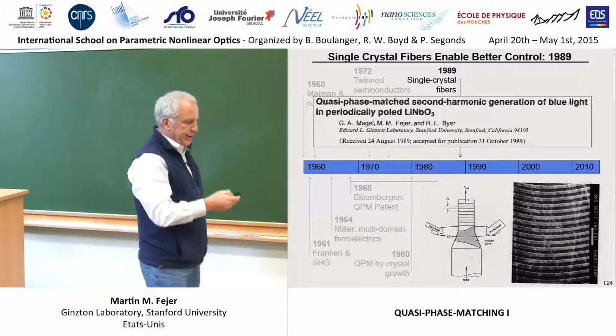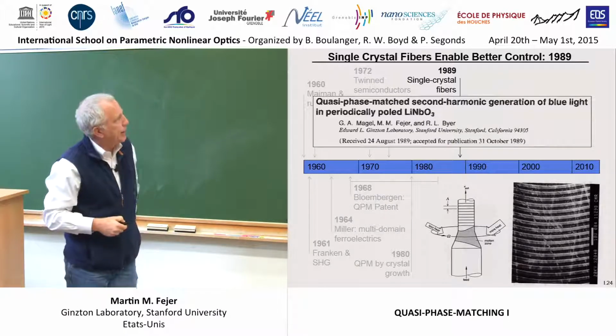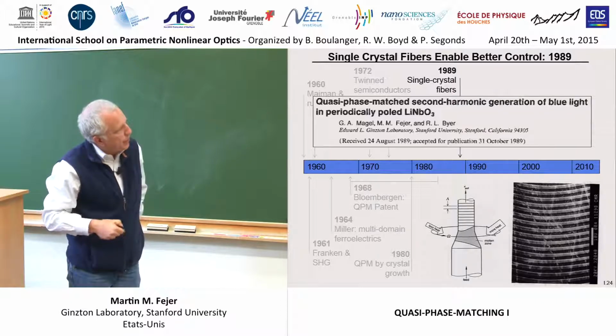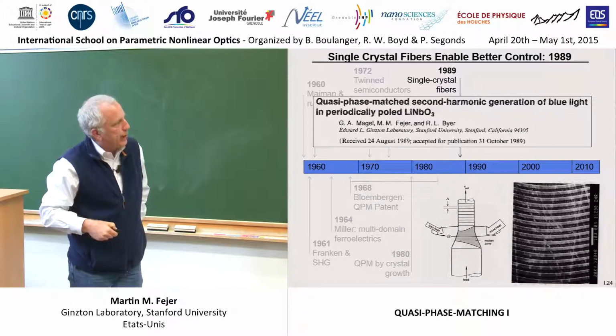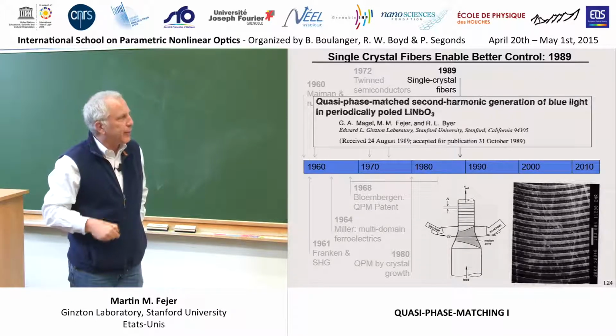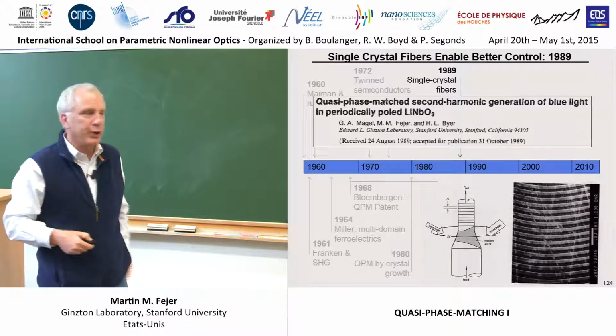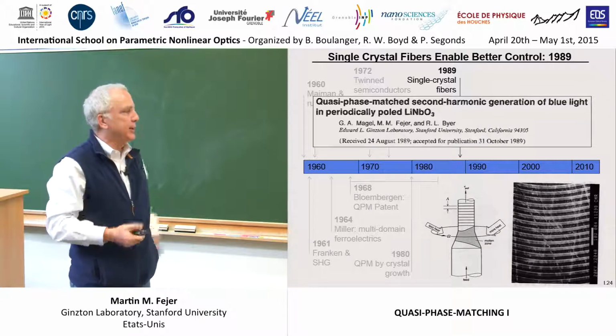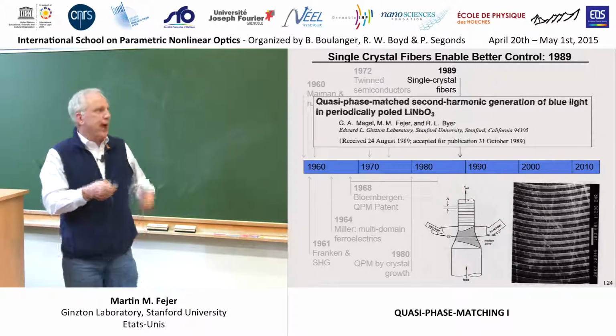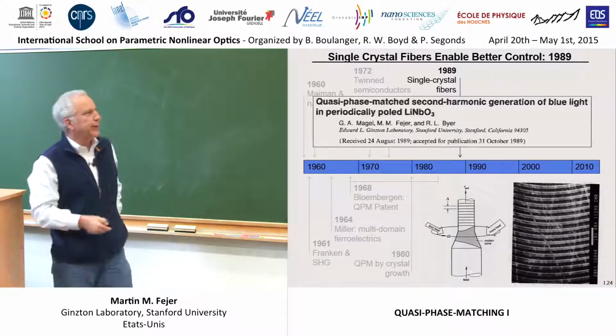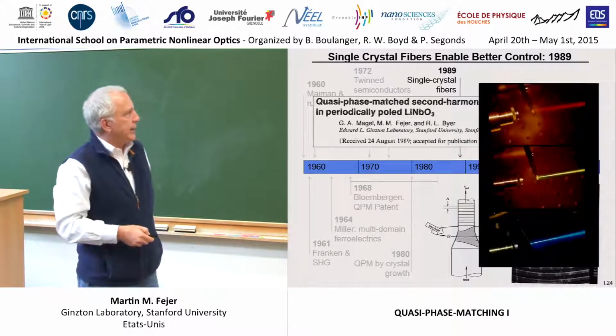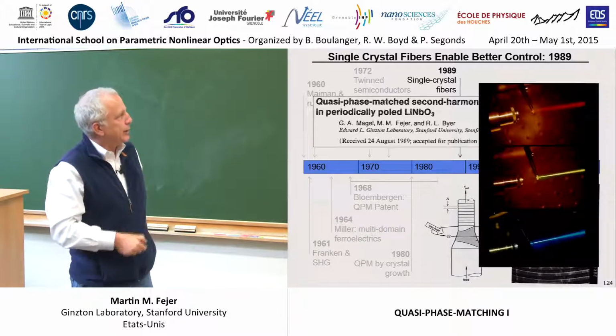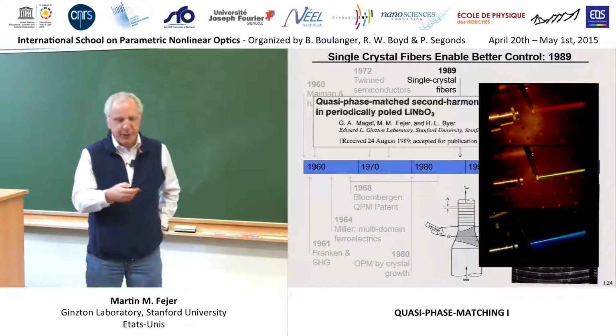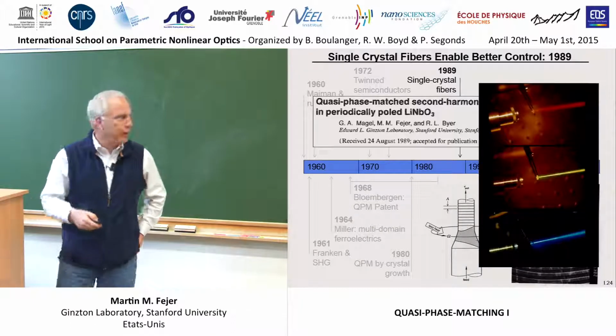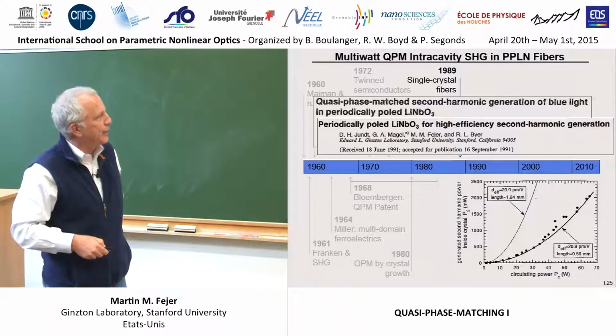We tried something similar back during my dissertation days, where we periodically perturbed a crystal, a single crystal fiber, a few hundred micron thick fiber of lithium niobate. The steeper temperature gradients helped stabilize that structure. We could get some periodicity. We could get some red, green, and blue light generation. This was the cover of a proposal to DARPA that got us a MURI that paid for a lot of the early work in this field.